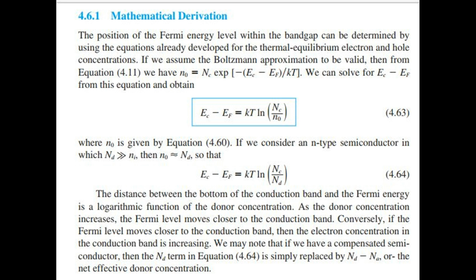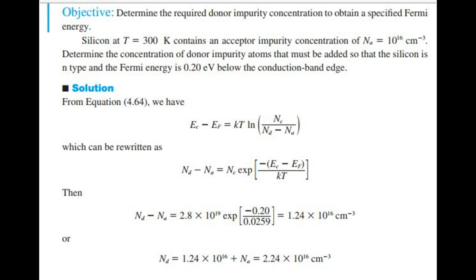Objective: determine the required donor impurity concentration to obtain a specified Fermi energy. Silicon at temperature T equals 300 kelvins contains an acceptor impurity concentration of Na equals 10 to the power 16 per cubic centimeter. Determine the concentration of donor impurity atoms that must be added so that the silicon is n-type and the Fermi energy is 0.20 electron volts below the conduction band edge.